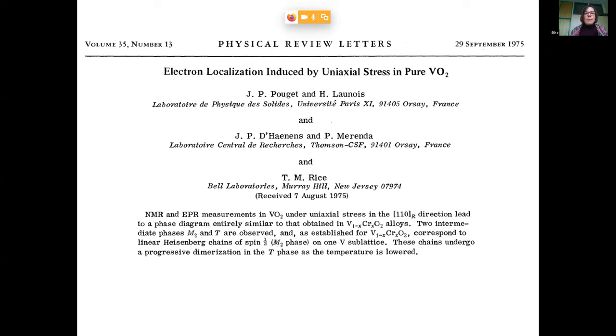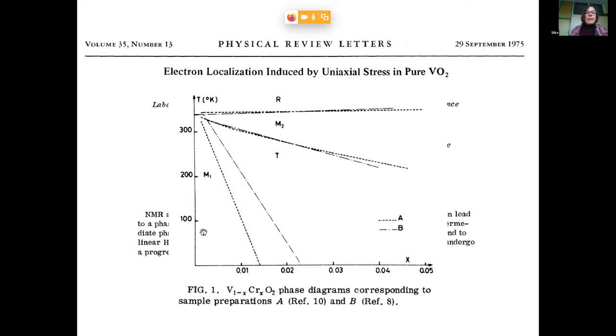So the fact that the whole phase was now insulating could be attributed to a Mott phenomenon. Their argument was that these phases are actually continuously connected to the initial phase without doping or without uniaxial pressure. Just for the nomenclature, the usual monoclinic phase we will refer to as the M1 phase, and the additional phases that were artificially introduced here are called M2 or tetragonal T. So you have the phase diagram with the metal-insulator transition slightly above room temperature, the low temperature M1 phase, and the high temperature R phase. When you chromium dope the system, you go to the tetragonal phase, the M2 phase, which are Mott insulators and which clearly emerge from the M1 phase.